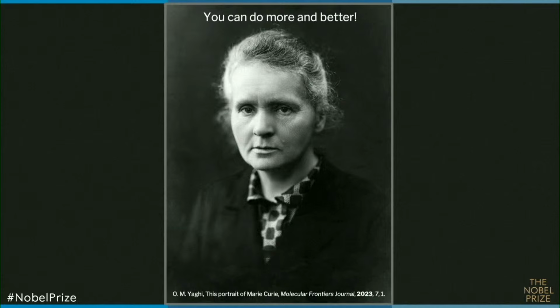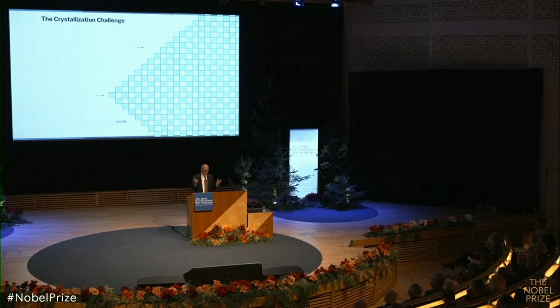So, let's get down to what is the challenge that we needed to solve first and foremost, and that's the crystallization challenge. The crystallization challenge is a challenge where you're taking building blocks and you're stitching them together now through strong bonds, and you need to make sure that on the microscopic level these building blocks can associate and dissociate so that they can correct their positions and make sure that you make an ordered material. If this reversibility is not present, then things will get stuck together and sometimes not at the proper orientation, and they will fall out as amorphous or non-crystalline materials. So that's one thing you need to ensure, that things can be bonded and broken on the microscopic level until they are fixed in position so that they are ordered.